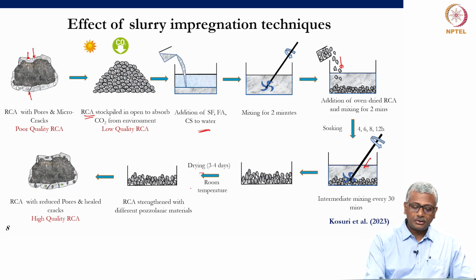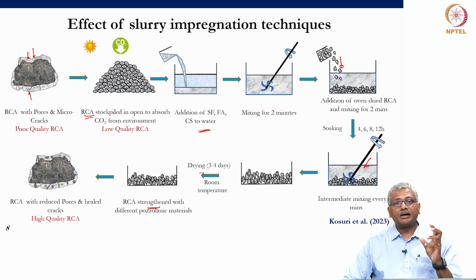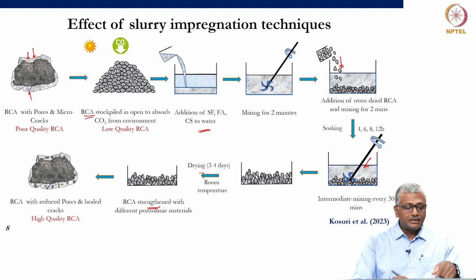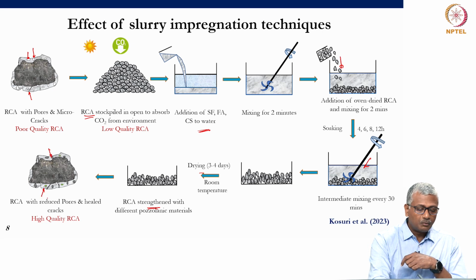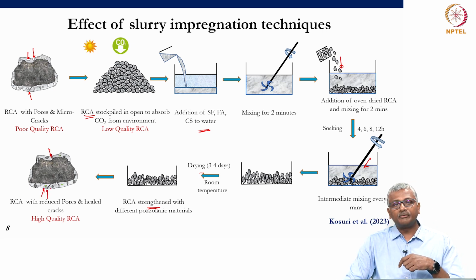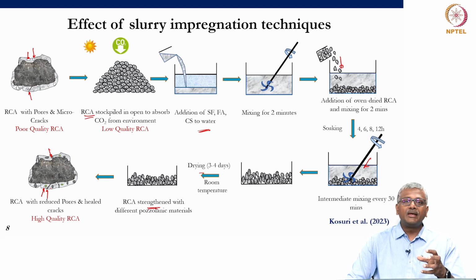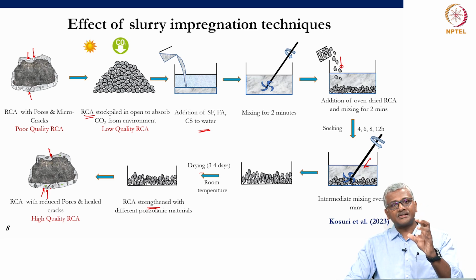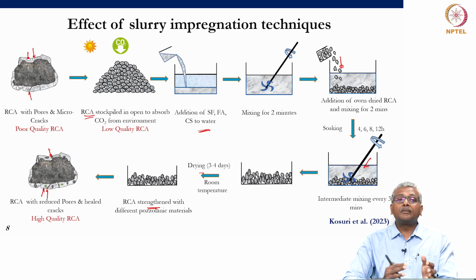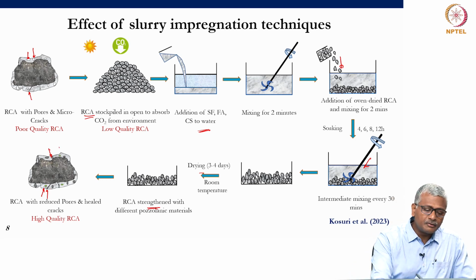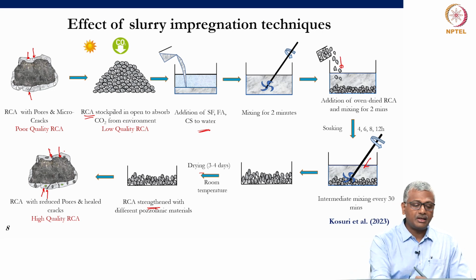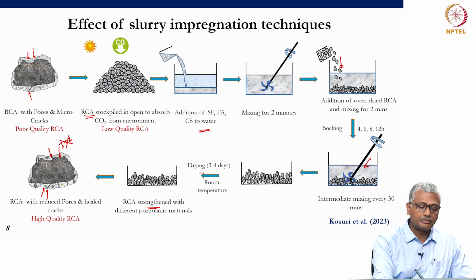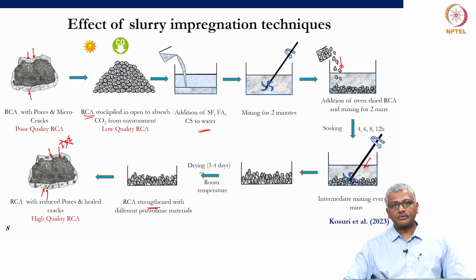And after drying, you will actually get the strengthened RCA, or recycled concrete aggregate, where the pores and fissures are now filled with the slurry material, right, which has been hardened because of the curing process. And now you have an aggregate that forms as a singular entity. The adhered mortar and the parent coarse aggregate are no longer much different. They have become a lot more uniform. In other words, you may not actually see the effect of the ITZ which was originally present because of the slurry impregnation. So, in other words, you are making the aggregate more homogeneous.